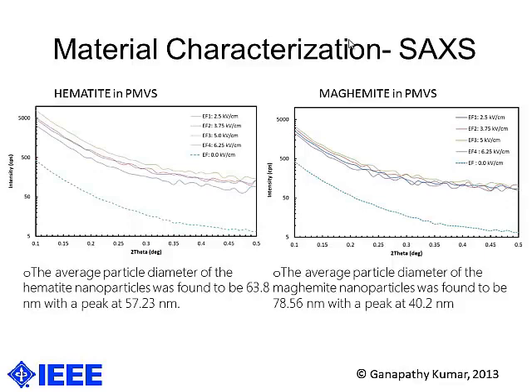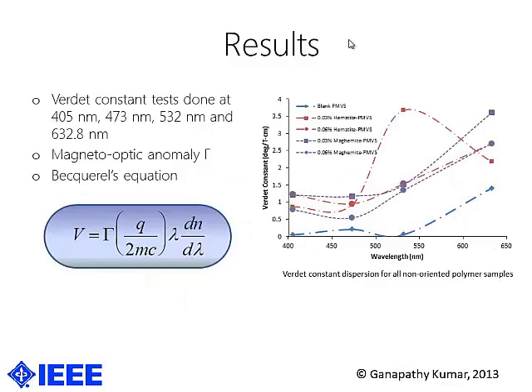Now, for the results, we tested the Verdet constant at 4 different wavelengths: 405 nanometers, 473 nanometers, 532, and 632.8. The main reason we did this was we wanted to gauge the potential of this material as a free space isolator, or a Faraday isolator, to name another moniker. So the magneto-optic anomaly, we computed it based on the control sample where we did not have any dopant, and we looked at how different dopants and different doping concentrations with different electric fields worked on this. So that's the Becquerel equation again.